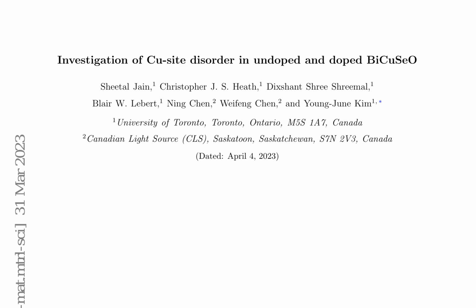The goodness of fit for EXAFS was evaluated using the reduced chi-squared value, which is often underestimated due to instrumental sources and errors in theoretical scattering factors. However, in the case of fluorescence measurements on very dilute samples, statistical variation is the primary source of measurement uncertainty, resulting in reduced chi-square values close to 1 for good fits, as observed in the Ag K-edge EXAFS data analysis.